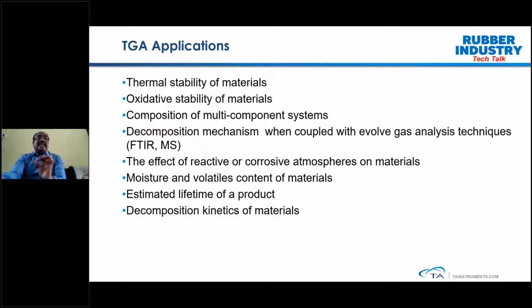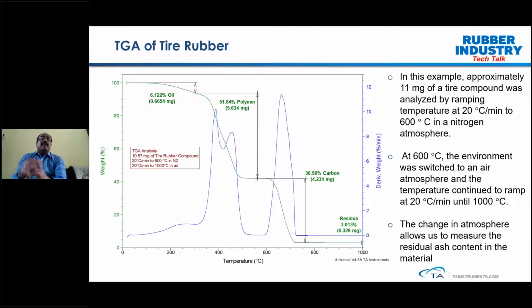So these are some of the key applications, and here I'm going to highlight some TGA applications in tire rubber. For example, this is a typical standard TGA thermogram where we took 11 mg of tire compound and analyzed it in ramping mode. Generally, it takes 10 to 20 mg of sample, put in a TGA crucible, which could be made of either platinum or ceramic, and then we heat it with a ramp of 20 degrees centigrade per minute up to 600 degrees under an inert atmosphere, in this case nitrogen as the inert gas.